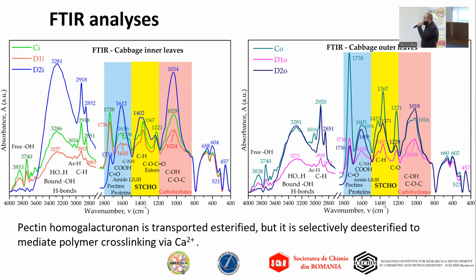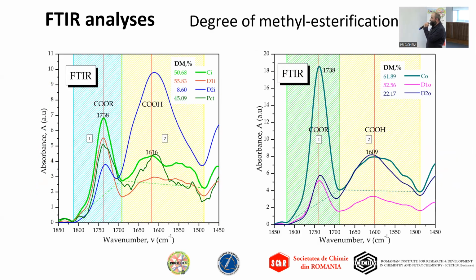Actually, we also see that the band corresponding to esterified pectin decreases with the increasing of dosage, which suggests that the selenium biostimulant stabilizes the pectin in cabbage in a non-esterified form. Also, the carboxyl and structural carbohydrates bands increase, suggesting biomass accumulation.